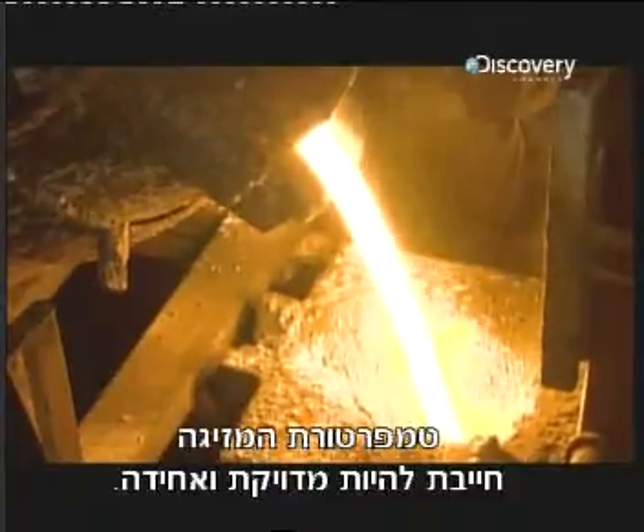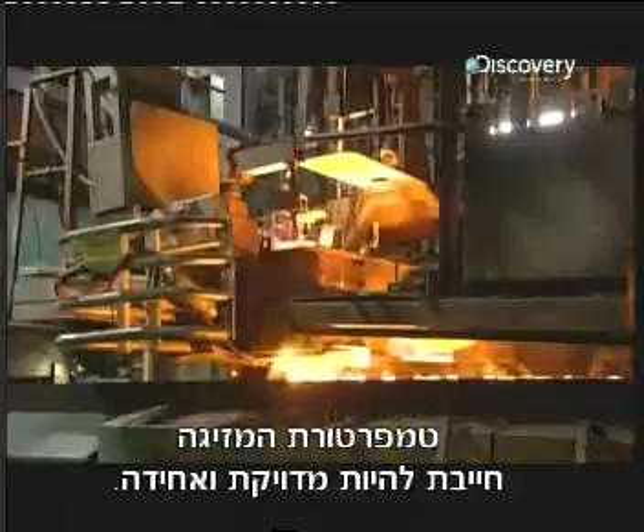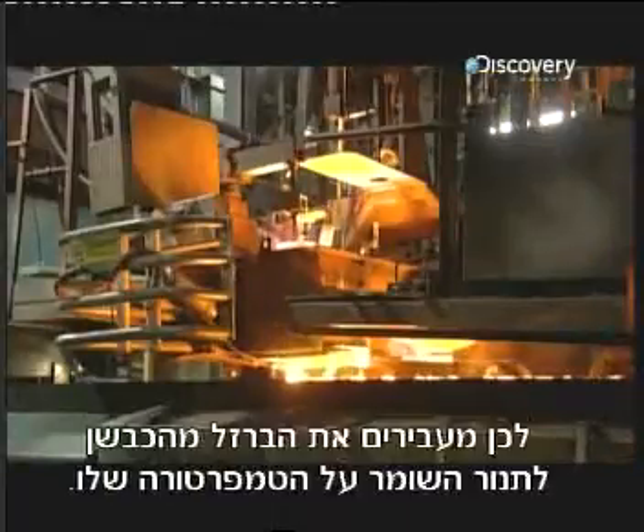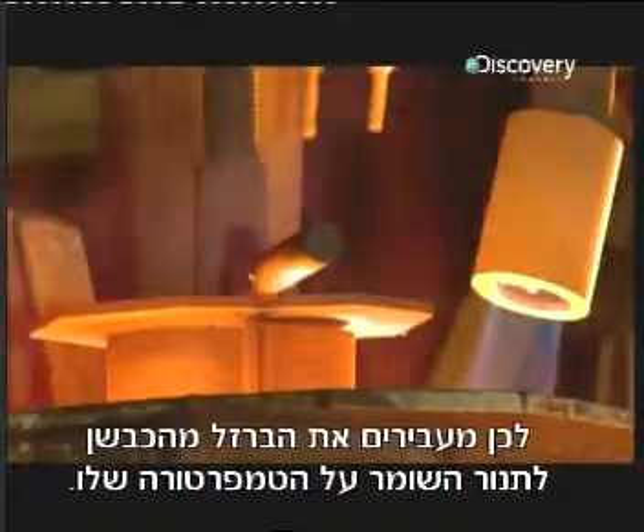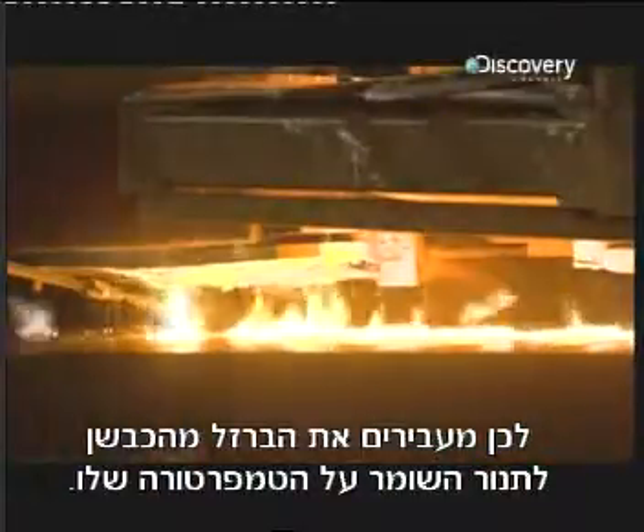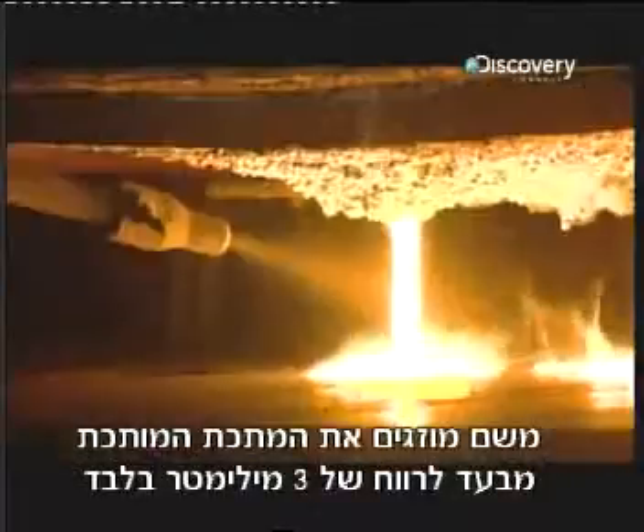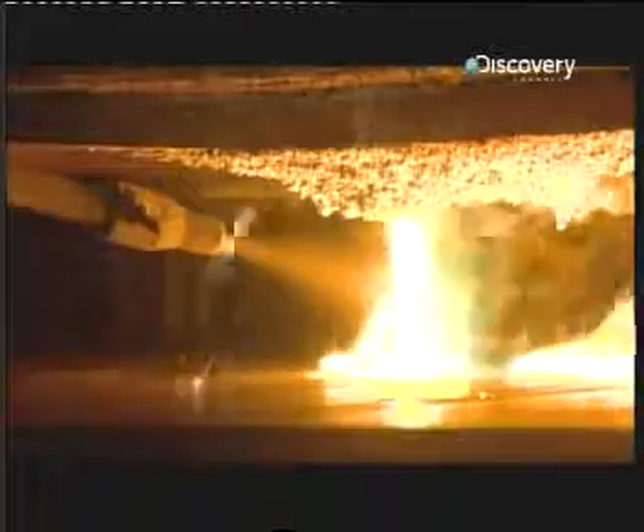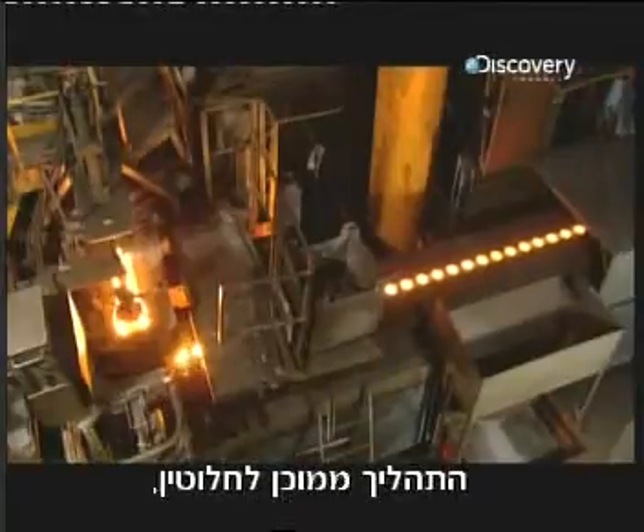It's essential that the pouring temperature be precise and consistent. So they transfer the iron from the furnace to a temperature maintenance oven. From there, they pour the molten metal through a mere 3 mm gap between the mold halves. The process is entirely automated because the pouring angle and speed are critical.